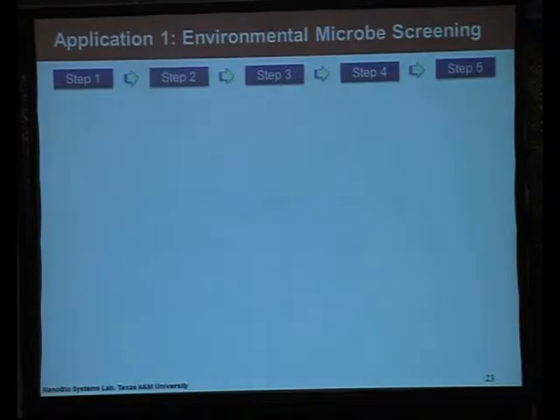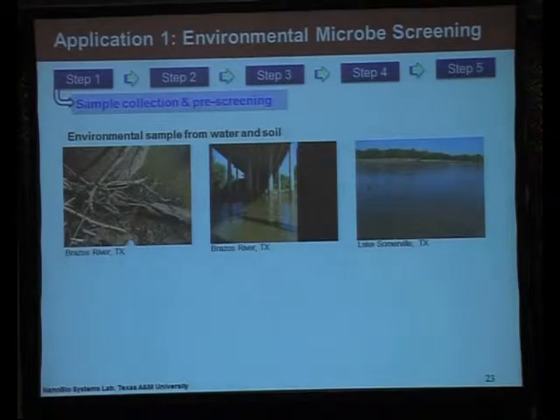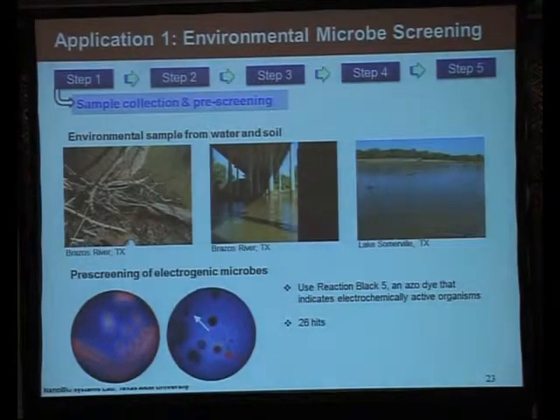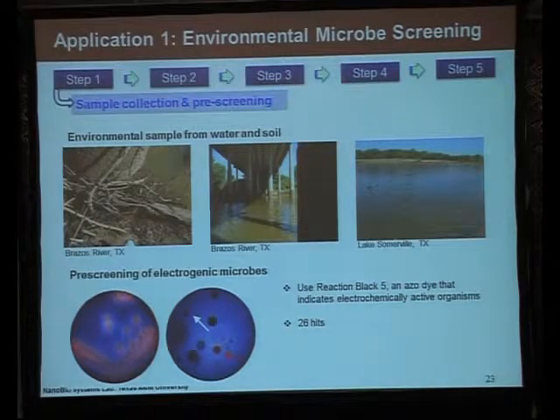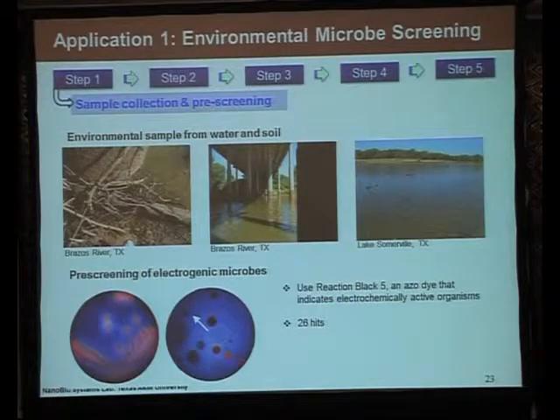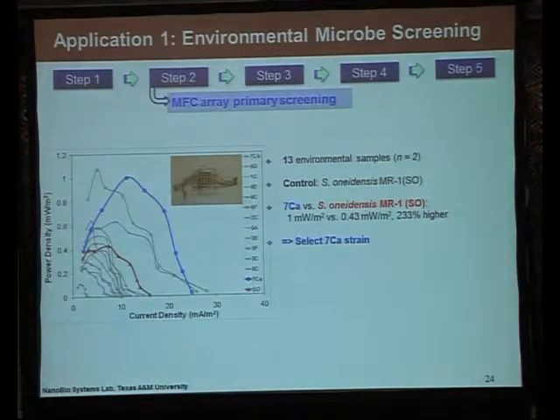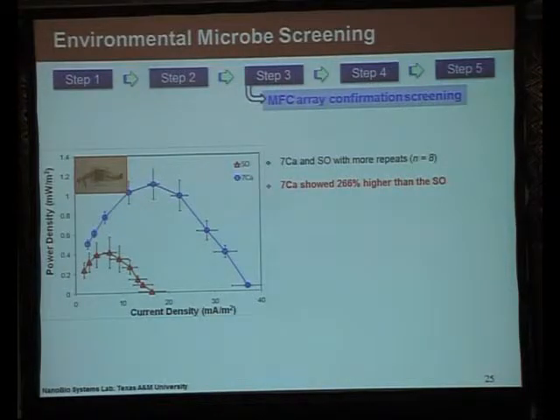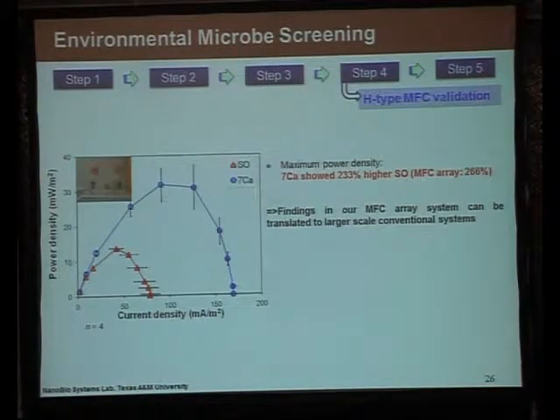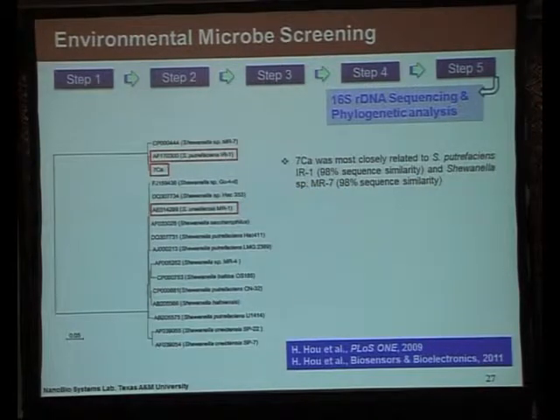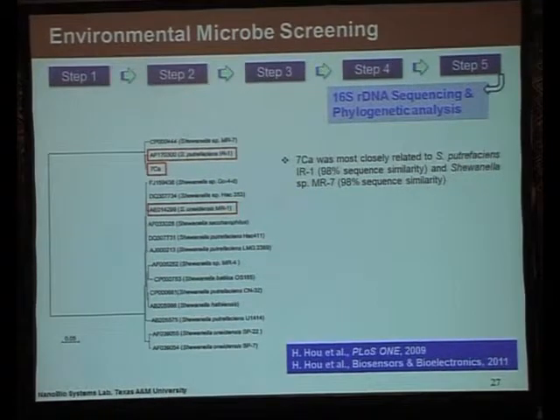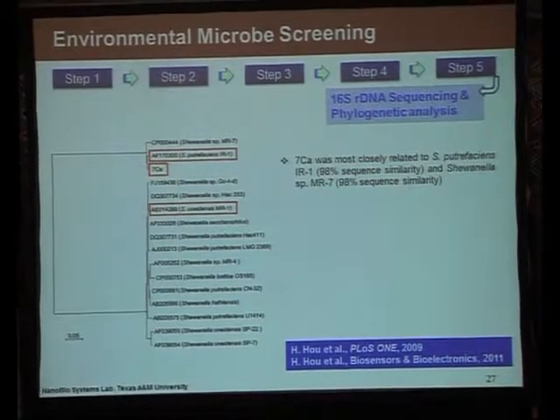We utilize this system to screen for environmental microbes. Initially we collect some samples and do pre-screening of these electrogenic microbes. What we're trying to do here is find highly efficient electrochemically active microbes from the environment. We do a primary screen using our MFCs to look at the power density, and we found some interesting microbes. We then do a confirmation screen using our screening device, as well as validation using a conventional system, and sequencing to find which particular microbes are producing this high power.